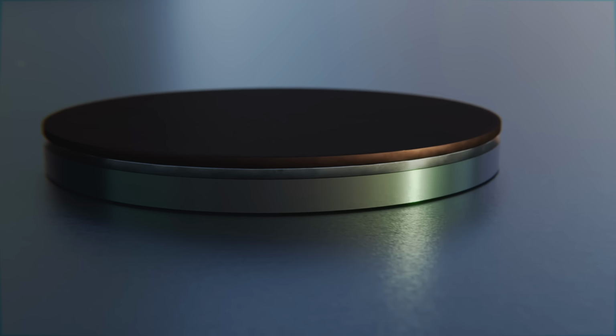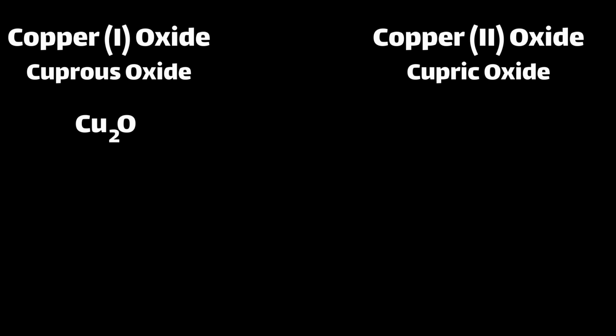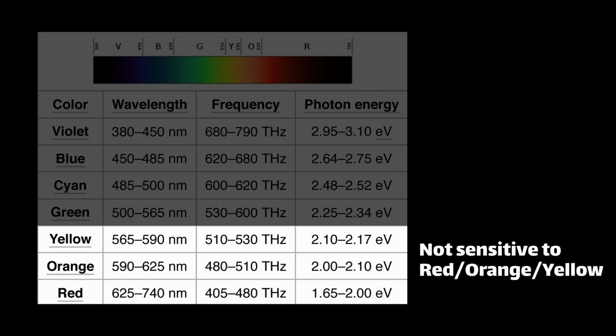This is where it starts to get a little complicated. So far, I've been saying copper oxide, but there are actually two different types. There's copper 1 oxide, also known as cuprous oxide, which has this formula. And then there's copper 2 oxide, also known as cupric oxide, having this formula. We're mostly interested in copper 2 oxide. Copper 1 is also a semiconductor, but has a larger band gap, around 2.1 electron volts, which means it's not quite as sensitive to visible light.